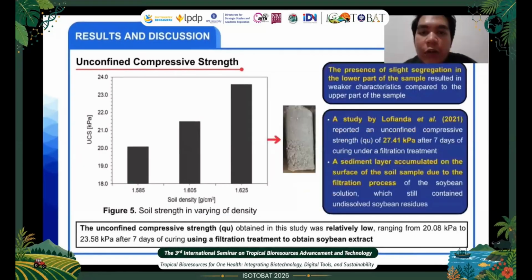The unconfined compressive strength values obtained in the study were relatively low. This was because of the slight segregation at the bottom of the sample, which resulted in weaker characteristics than those of the upper portion. This occurred because of the accumulation of a sediment layer on the surface of the sandy soil sample, as the soy extract filtration process left behind some insoluble soy mass, which affected the distribution of calcite in the soil.